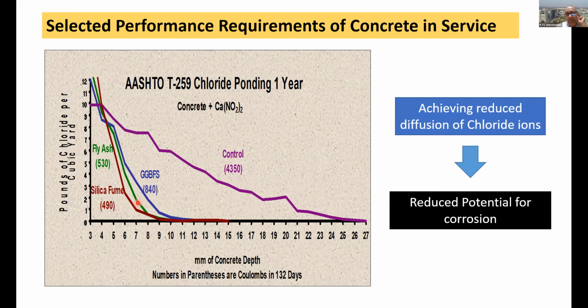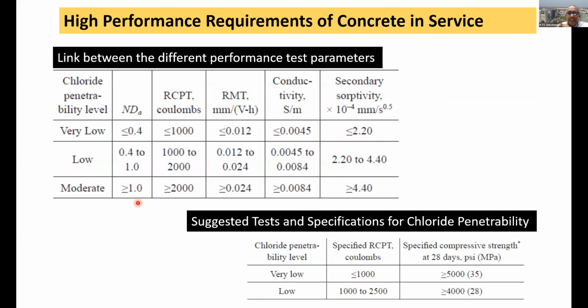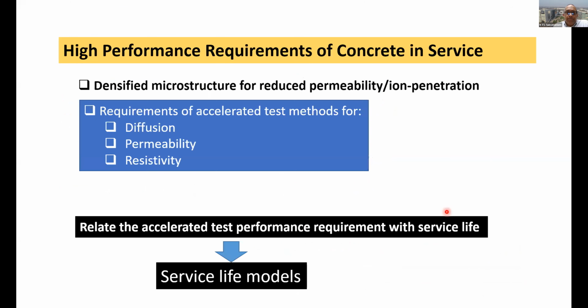Now, we've also developed these rapid test procedures like the rapid chloride penetration test, which allow us to specify measures that I can put in place to ensure, let's say specifically for chlorides, that the concrete is durable against chloride penetration. And typically the way we achieve this limitation of chloride penetration is by densifying the microstructure. We basically make the microstructure very dense by adding fillers. And of course, we have accelerated test methods for diffusion, permeability, and resistivity that help us assess if what we have done is correct.